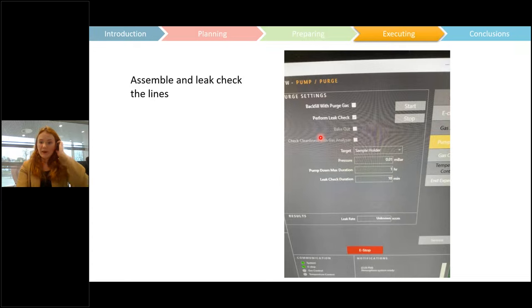So yeah, here you can see where I would leak check the line. So I go down to 0.01 millibar and I don't actually check for 10 minutes. I just wait and see if it goes down that far. But making sure that those lines are really tight to the back of the holder is really, really important. Something you should know is the ferrules, if you get new ones, they have like a breaking in period where you have to really, really tighten them and it's a bit scary. So if you get new ones, be really extra careful and check this because they can spring leaks quite quickly.